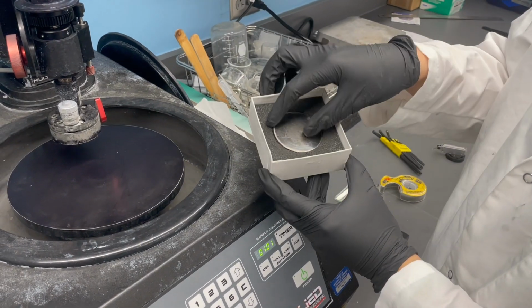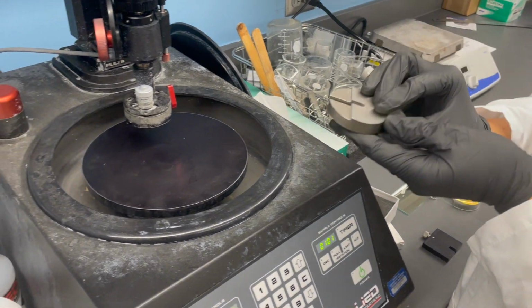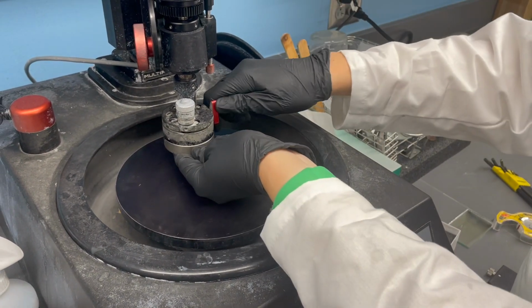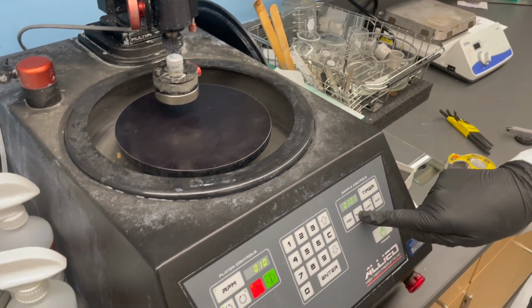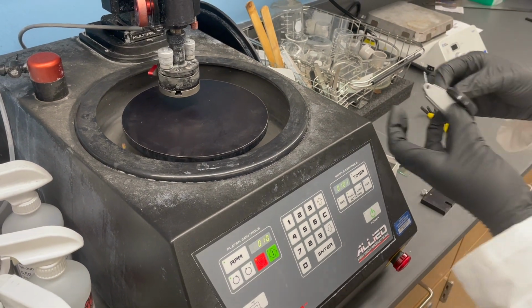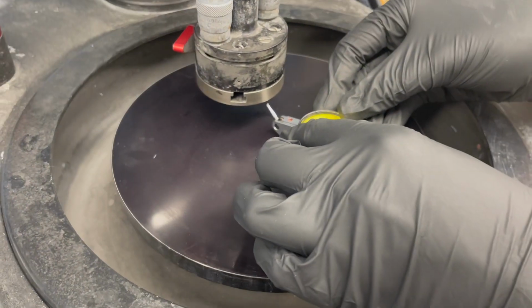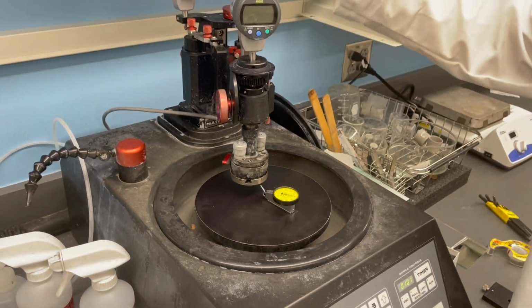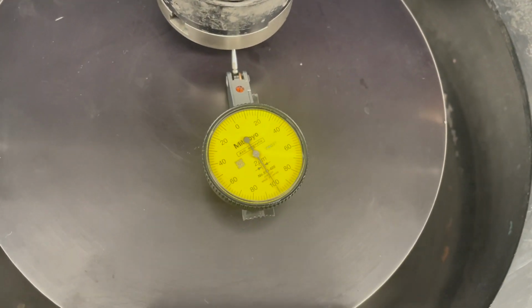Take out the calibration polishing fixture and attach it to the head and tighten the red pin. Press the full button until the silver screw is at the 6 o'clock position. Align the screw with the dial arm and attach the dial on the platen where the arm is at the edge of the fixture. Lower the arm until the dial reads 0.